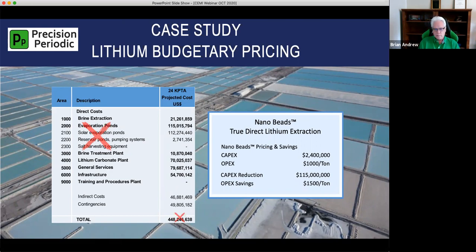Basically you have a wellhead, a couple of filters in a small building, and then you put the water back down into the ground, and that's it. So your CapEx is hugely reduced. But your OpEx is also reduced if you're only using water as the active ingredient to wash out your lithium, as opposed to thousands of tons of precipitant chemistry, which is used today.